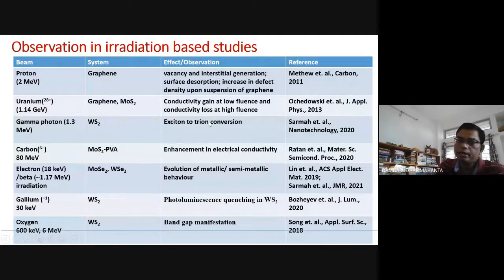And in fact, one day it is possible that we can have two terminal or three terminal devices where electron transport can be replaced by trion transport, which are actually charged excitons. When we write exciton, these are neutral excitons, EH, which will act as a boson, a single entity, whereas a trion is a charged particle, EHH or EEH. So there is enhancement in electrical conductivity in this case, and evolution of metallic, semi-metallic behavior, as I have mentioned. People have also reported this type of behavior in MoSe2 system, then photoluminescence quenching and band gap manifestation.